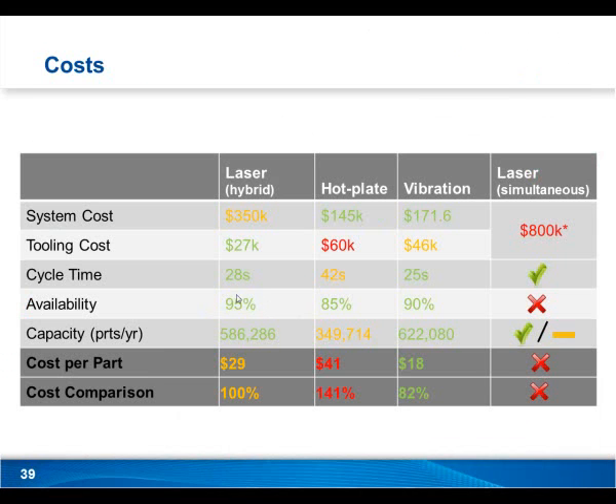So your downtime is going to be about 5% compared to where you have higher maintenance costs with, say, hot plate or vibration, or very high with laser simultaneous. So I don't have a hard cost factor for you, but compared to these other methods, your maintenance costs are going to be lower. The lasers themselves tend to run for tens of thousands of hours. We don't like to throw out an exact quote, but it can be between 10,000 and 20,000 hours for a laser source before they start to really require any maintenance on them. Other than that, the machines are designed to run 24/7, 365.